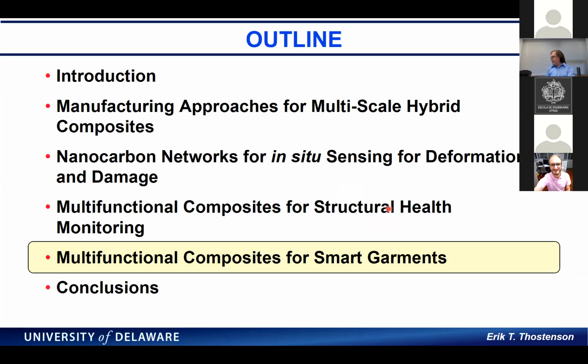Okay, so the last part I want to talk about for maybe the next 10 minutes is this new area over the past probably 2 or 3 years that we've been working on: multifunctional composites for smart garments. And actually the coating that is applied to the individual fibers that you saw earlier is not just nanotubes or nanoparticles sitting on the surface, but they're chemically bonded to the surface, and chemically bonded to each other. So it creates almost like a sponge-like porous nanocomposite film.